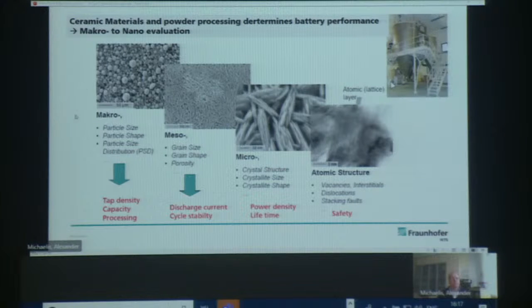And of course, this is good for the performance of a battery because then a lot of charge can be stored in such a battery. But here on different scales, it's shown that this is not sufficient only to make this spherical morphology. When you zoom into such a sphere, you see here that each of these particles has again to show a certain kind of morphology, a porous structure in order to allow the electrolyte penetrating into the whole volume. And the whole thing is optimized down to the atomic scale in order to improve the performance of a battery, safety-wise, power density-wise, energy-wise. Here a lot of optimizations can be done applying ceramic know-how. That's what we are doing.